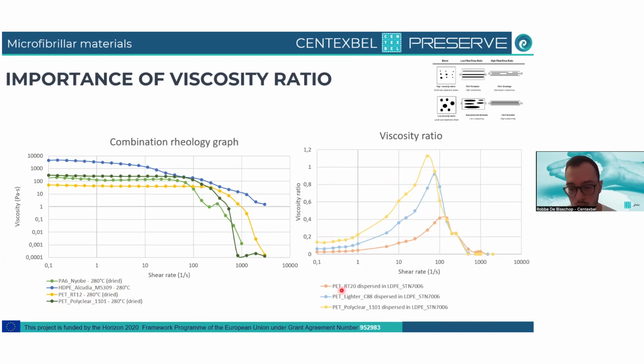And then you can see, the yellow graph is the PET, a polyclear, so a grade of the PET dispersed in the bio-based LDPE. And then the blue graph is another PET, and the red graph is also another PET. If we look at cast film extrusion, we look around a shear rate of 100. If you look at this, you can have a viscosity ratio of 0.4, but also a viscosity ratio of 0.8.